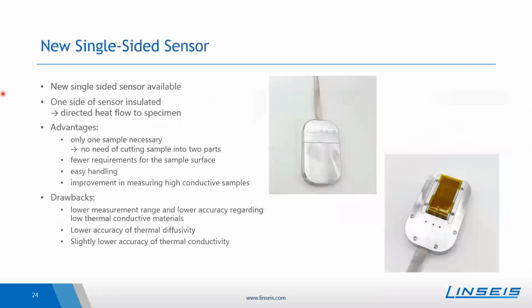What is new available is our single-sided sensor. Here, one side of the sensor is insulated, so one has a more or less directed heat flow to the specimen. And the advantage of the single-sided sensor is that one just needs one sample piece, and because of that, it is a non-destructive measurement, because typically one has a piece of material and then needs to cut it into 2 parts to be able to sandwich a sensor. Here, this is not necessary.